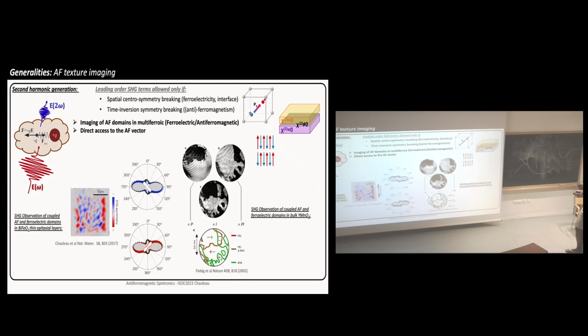And a couple of years ago, we've done that, for example. It works also in thin layers, where the red and blue contrast actually stands for the antiferromagnetic domains in what I have not put here, but you have to trust me, a single ferroelectric monodomain. So this is to prove that we can directly access the antiferromagnetic vectors using this SHG system.